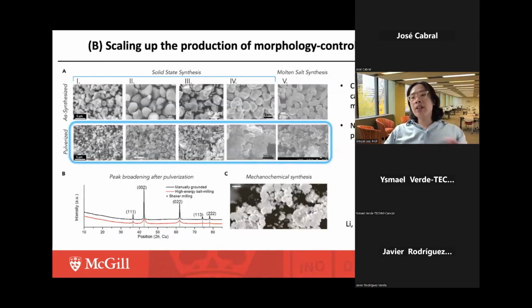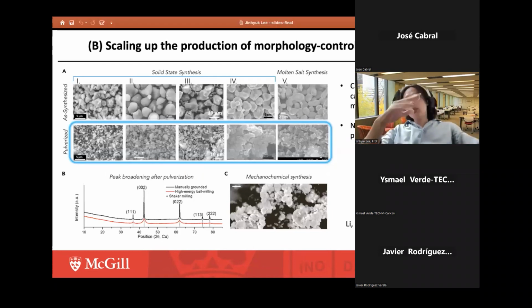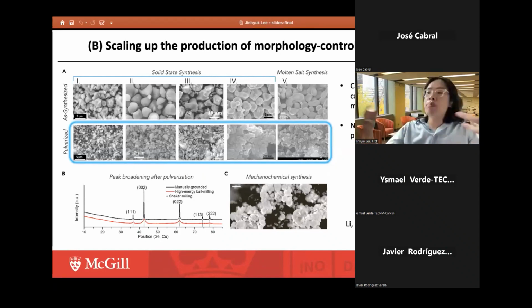And I would like to say that in addition to this, it's very important for us to come up with a scalable production method of morphology-controlled DRX particles, because current DRX materials that have been synthesized cannot be mass produced with controlled morphology. Typically people use so-called solid state synthesis followed by particle pulverization, or mechanochemistry, which also involves particle pulverization. So in the end, you basically produce pulverized particles.